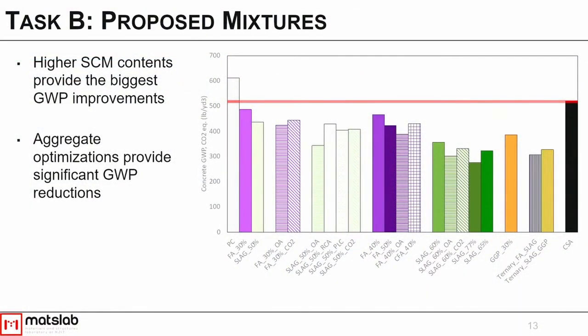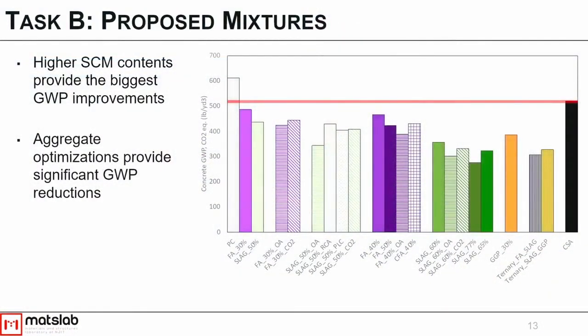So this is our GWP per our original proposed mixtures. You can see what the GWP might be for the various systems that we did. These include some emissions associated with fly ash and slag. What we used for that was essentially a cost balance, or a profit balance. If we assume the company makes money off of selling the fly ash, we allocated some of the emissions to the production of the fly ash. It's controversial whether you should do that or not. There's a lot of debate in the field, but we chose to do that. If we didn't, the emissions would probably be lower, so this is a more conservative view of the emissions associated with the fly ash and slag.